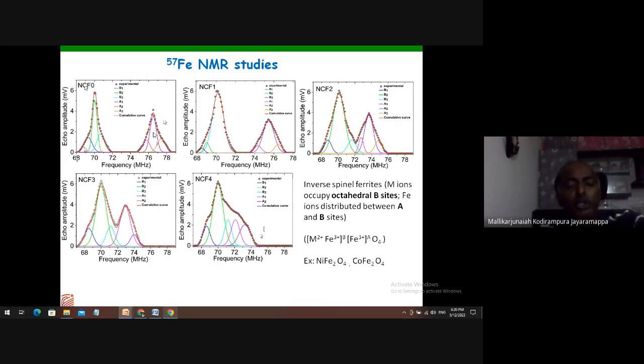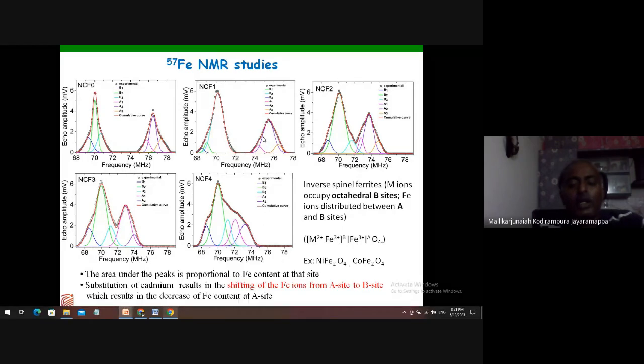With a little more detailed analysis using other conventional spectroscopic techniques, we were able to measure exactly what percentage of ions got distributed among these two sites, and as a function of the addition of cadmium ions, how cation redistribution has happened, quantitatively. That work was done here and was very well reported. That kind of microscopic information is hard to get from other techniques except the Mössbauer technique. Also, we can get similar type of information.